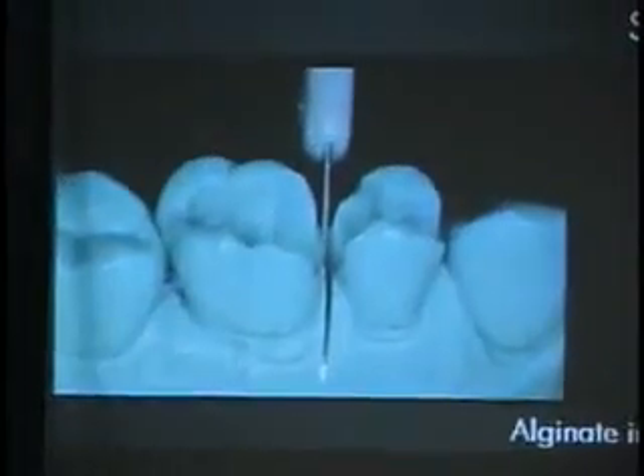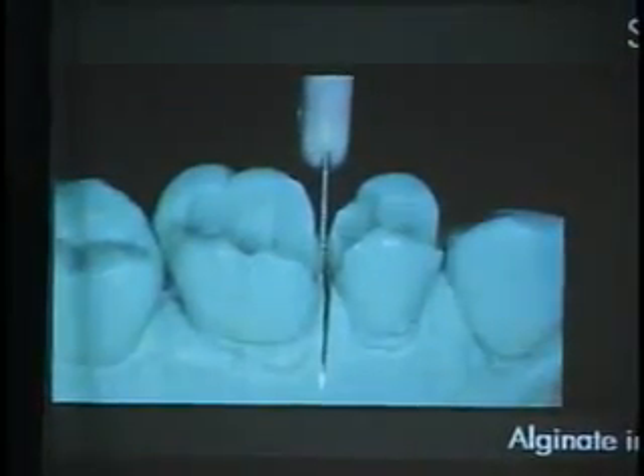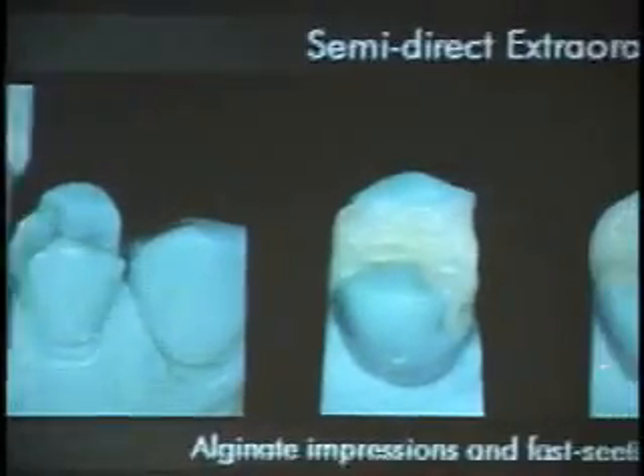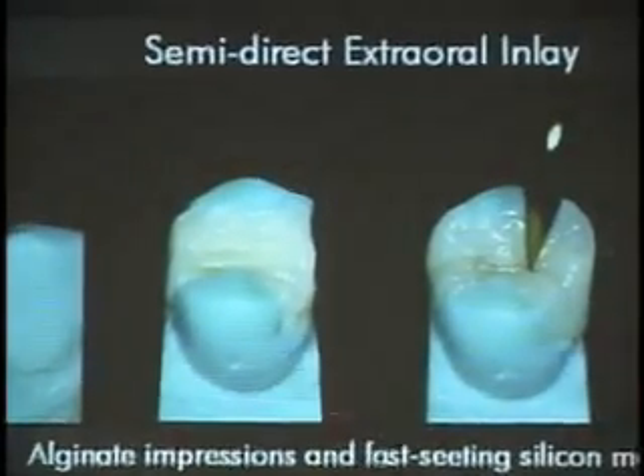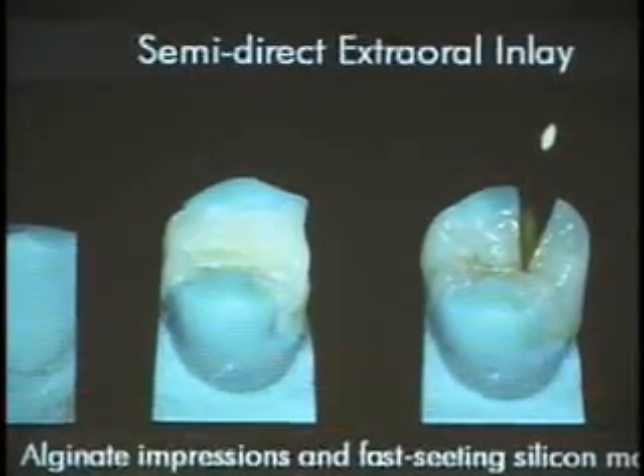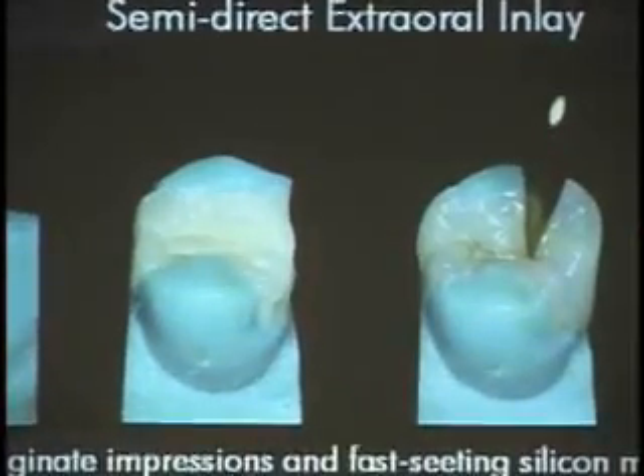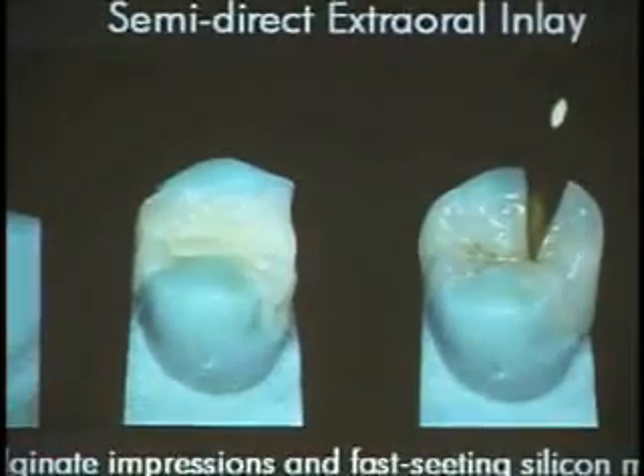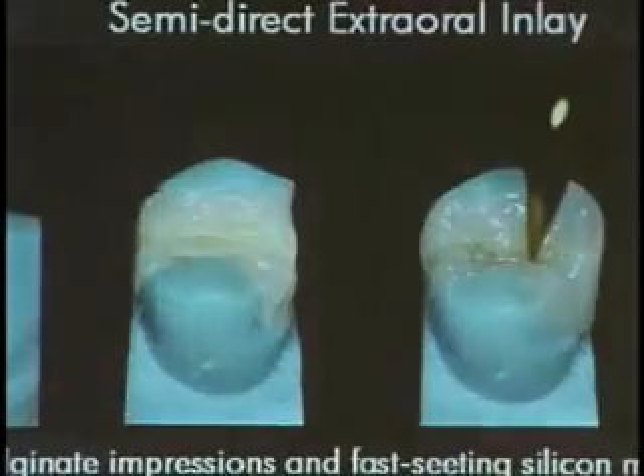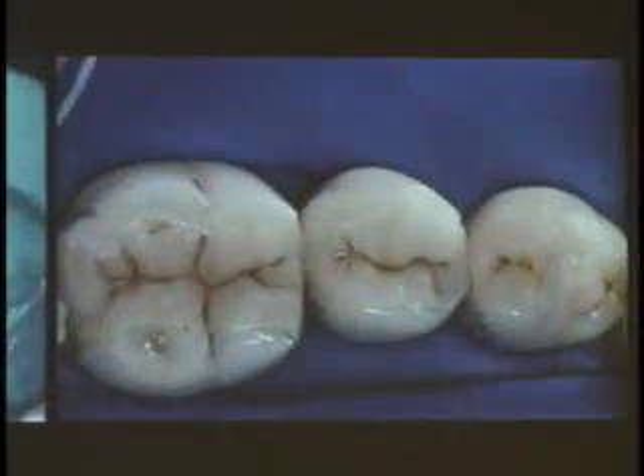That's why I like very much the next technique, which is called the semi-direct extraoral inlay, in which we take a small impression, and it can be an alginate impression of the cavity, and we have a fast-setting silicone model. These were the first generations of this fast-setting silicone that you can fabricate in minutes in an alginate impression. It's not like stone, where you have to wait and it's difficult to section the model. Here you can section the model with a blade, and then you layer, you put it in the oven, you post-cure, and you can place it in the mouth.